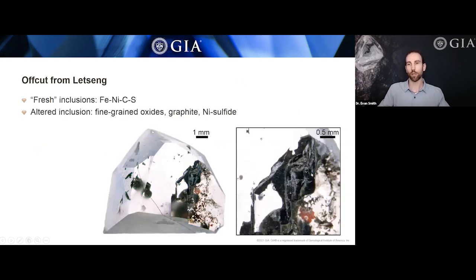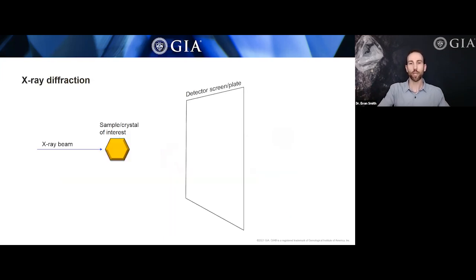So here's just a close-up on that particular inclusion, and this is the inclusion we're going to be talking about, where we discovered this new mineral. So one of the first things I did with this inclusion to analyze it in more detail was use X-ray diffraction. And X-ray diffraction is a technique where you pass some kind of an X-ray beam into your sample or crystal of interest. And a lot of the X-ray beam passes right through onto whatever detector you have.